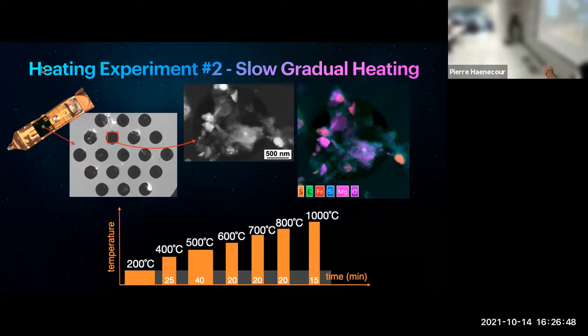In this case, we did a way more gradual heating, not doing any flash heating, going from 200 degrees for a long period of time to 400, 500, 600, 700, 800, and then finishing at 1,000 degrees, all for about 20 minutes or longer. This particular time was chosen randomly. It was just to try as a first test, to see how gradual heating was working for us and see where the most changes actually happen.